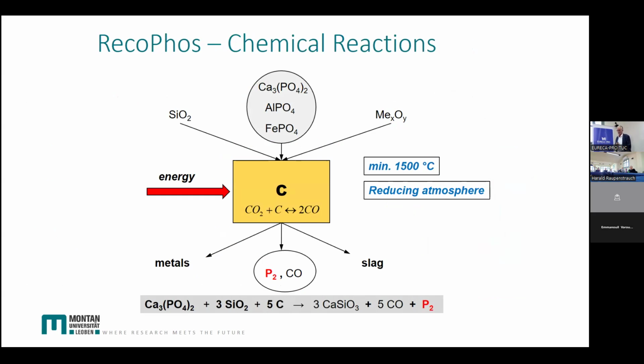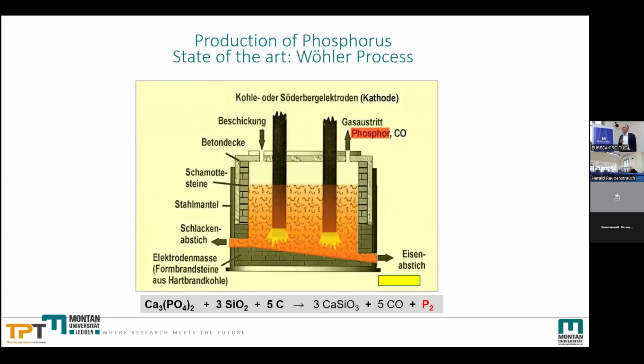This is the main reaction to produce phosphorus out of the sewage sludge. You have this bound phosphorus in this calcium phosphate, and you need silicon oxide for slag formation. You need carbon because this chemical reaction takes place under reducing atmosphere, because in this case you can reduce the phosphorus oxide, produce phosphorus and carbon monoxide. So that sounds quite simple. It's similarly done with the rock phosphate by the Wöhler process. This is commonly known, so the same chemical reaction takes place there.